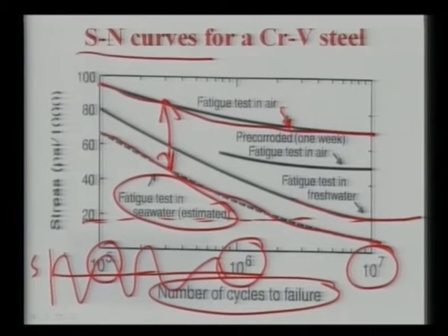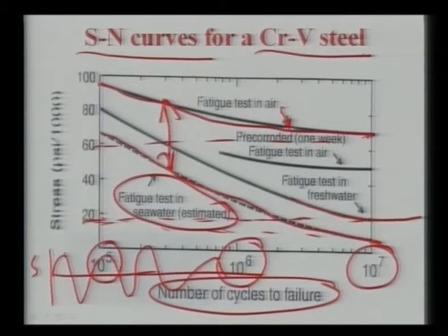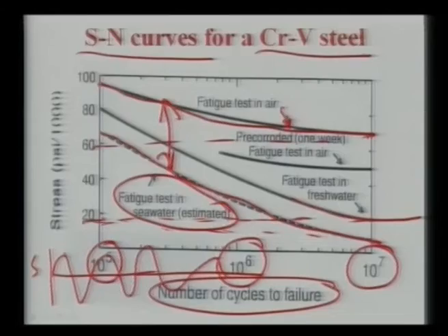Also, the fatigue strength here is around 60 megapascal. In case of the fatigue test in seawater, it is even less than 20 MPa. So it is a 3 times decrease in the fatigue strength of this chromium vanadium containing steel. This is just an illustration; this kind of behavior is also reflected in other materials. So the general message from this slide is that fatigue behavior in seawater is degraded compared to the same behavior in simple air or ambient condition.